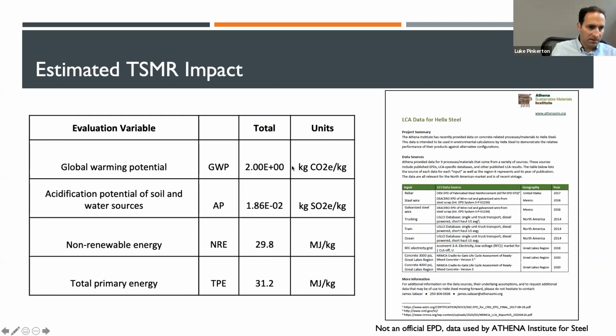You can see that the twisted steel micro reinforcement has about 2 kilograms per kilogram of CO2. So it's definitely a bit higher, but that makes sense because compared to rebar, rebar is just hot rolled. Twisted steel micro reinforcement is actually made from hard drawn, so it's cold work steel. It starts with hot rolled rod, and then it's drawn out by stretching it to a smaller diameter, and then it has to be twisted as well. So it makes more sense because a lot more energy goes into that process. The good news is that Helix twisted steel micro reinforcement is more efficient than rebar. So we make up for that in other ways, and I'll show you how that happens in a minute. So the actual impact ends up being lower than the rebar.